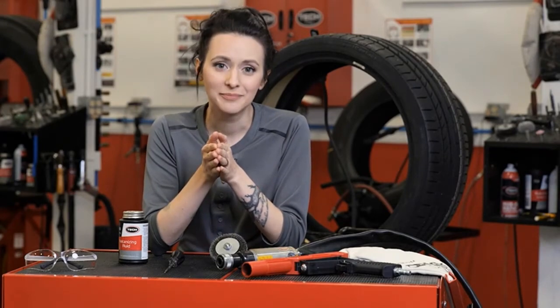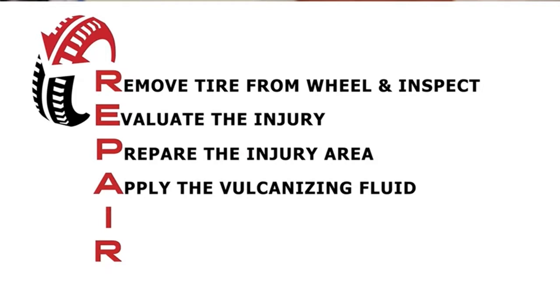You need to allow approximately 3 to 5 minutes for the vulcanizing fluid to dry. Additional drying time is required in cold and humid climates. Vulcanizing fluid must be completely dry before applying the repair to avoid trapping solvent under the repair, which could create air bubbles and ultimately result in the repair failing. There you have it. This concludes the Tech Sound Suppression Tire Puncture Repair course, applying the vulcanizing fluid.